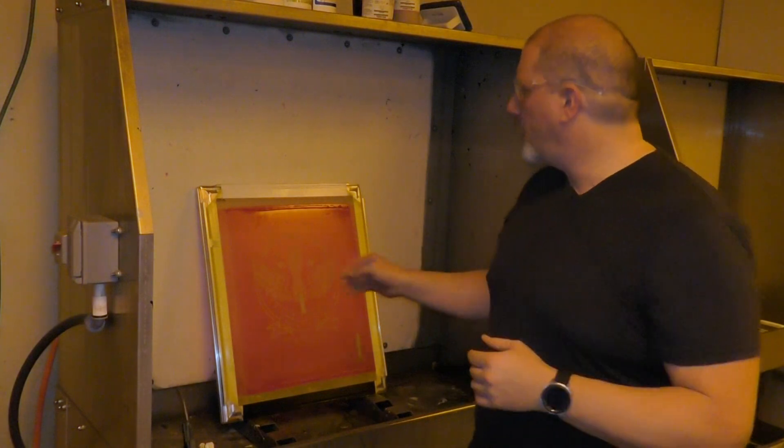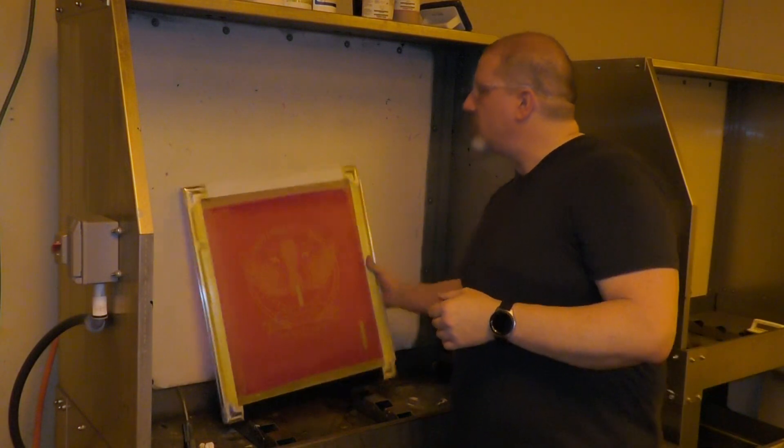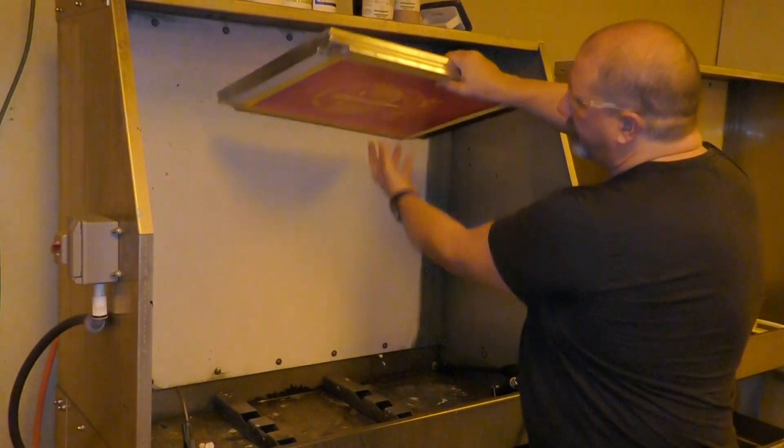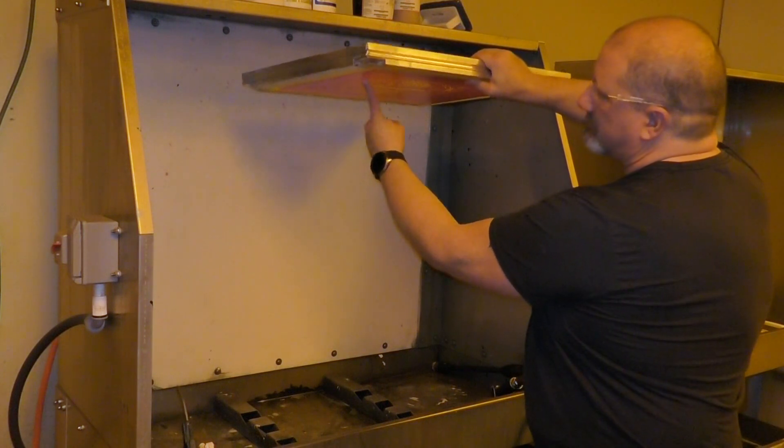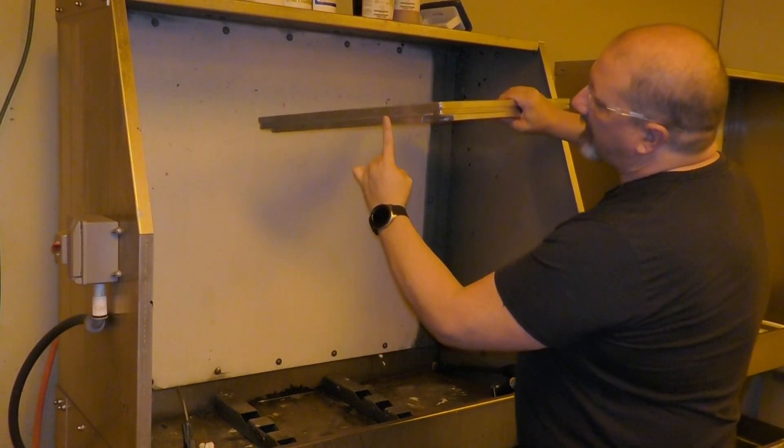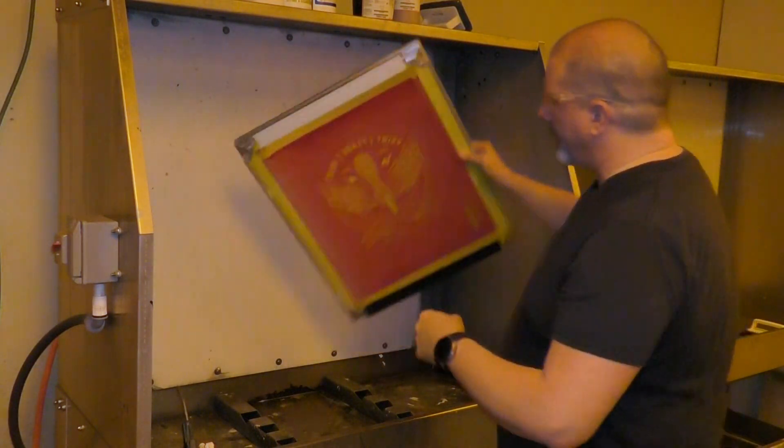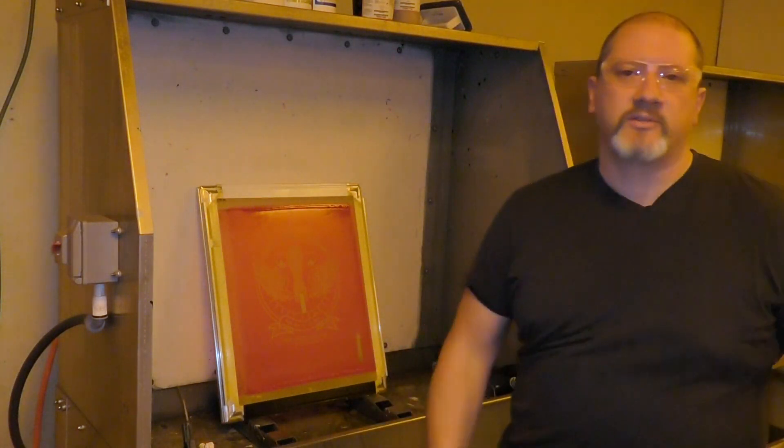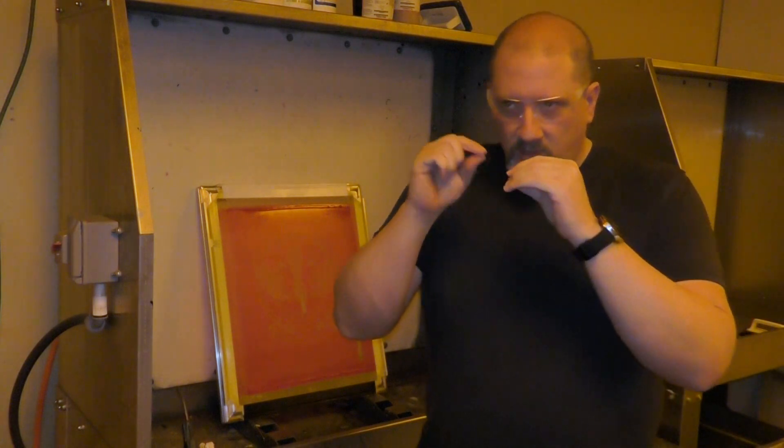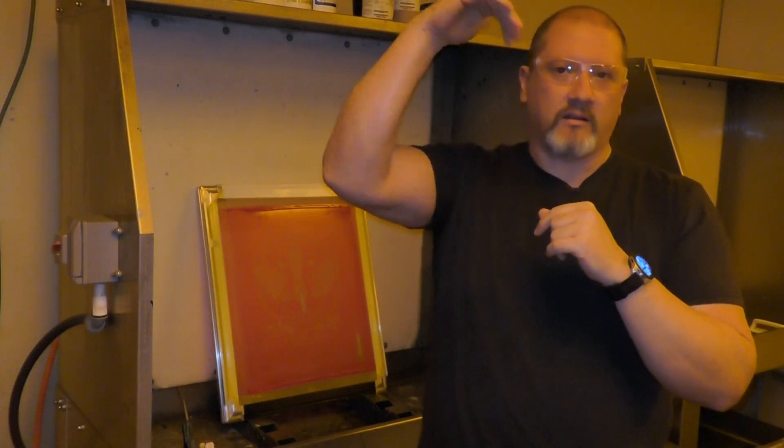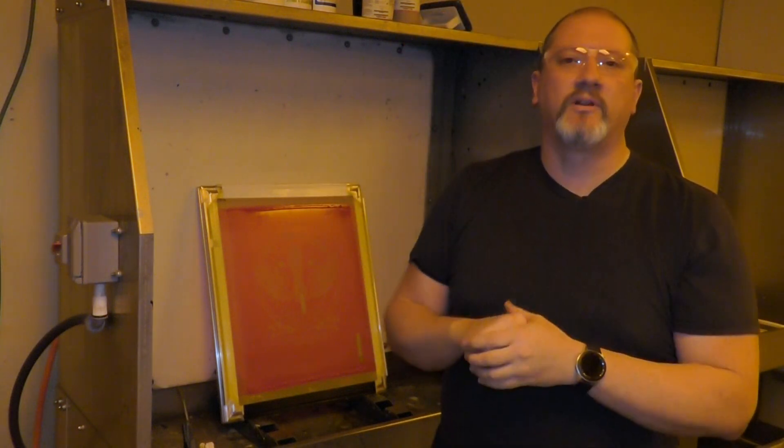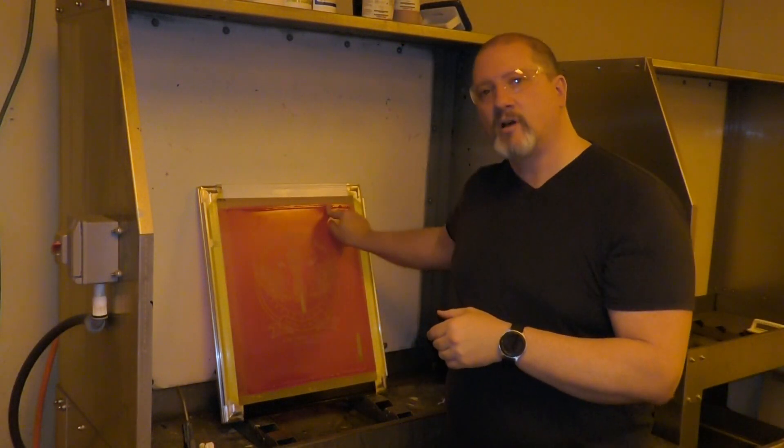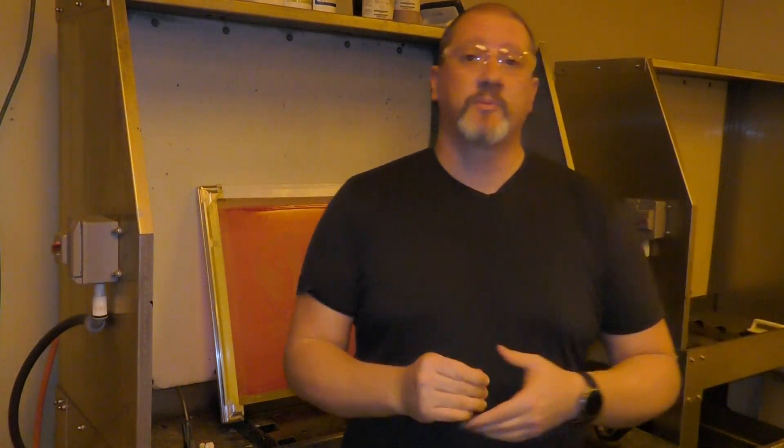When we expose our screen, whether it's this way with the light underneath, the light always hits that t-shirt side first and then it's got to travel through all the way up to your squeegee side. If we stop that exposure where we get a full solid step seven, we don't get the same level of exposure up at the thicker parts of our emulsion. So it's underexposed. That area will not break down properly when you're using a stencil remover. It's going to come off in strips. It's going to be gummy. It's going to get sticky and just not want to come off depending on several situations.